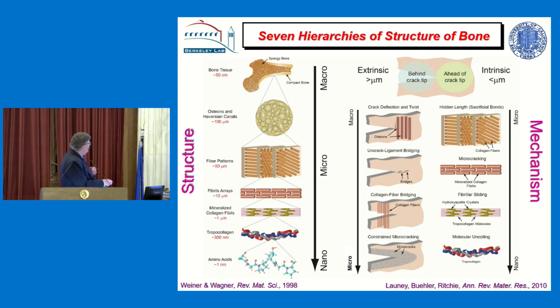And as we look below a micron, the main mechanism of toughening in bone is what we call the intrinsic mechanism. It's the resistance to fracture. And that resistance to fracture is caused by the collagen being stretched. But after it stretches a little bit, it sort of locks, as we call fibril sliding. The fibrils, those twisted collagen molecules with a little bit of mineral in, slide apart. So if there's any resistance to that sliding, the material becomes stronger, but it can cut down its ductility and hence its toughness. So one of the toughening mechanisms, or lack of toughening mechanisms, is this fibrillar sliding. As long as the fibrils can slide, we're okay. If they lock up, we have a problem.